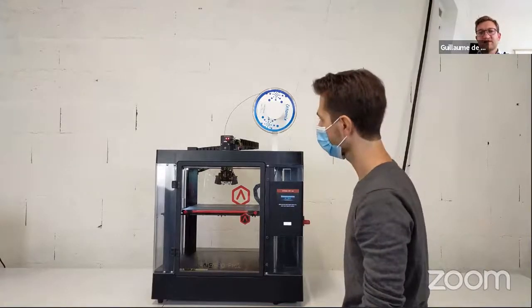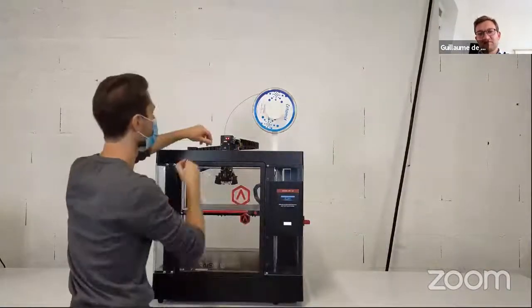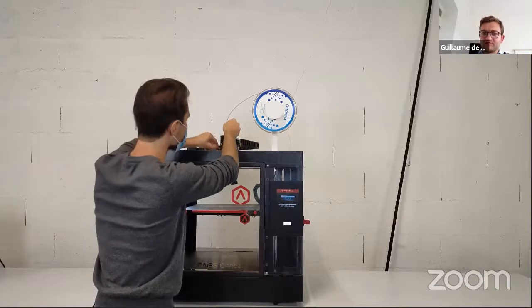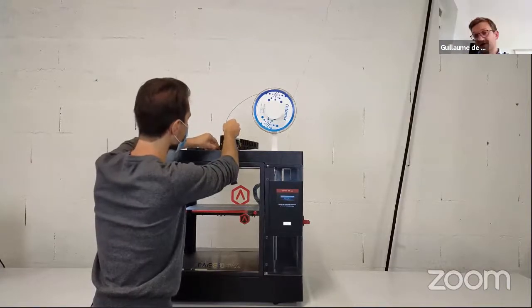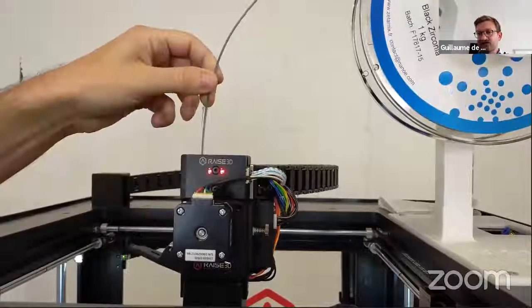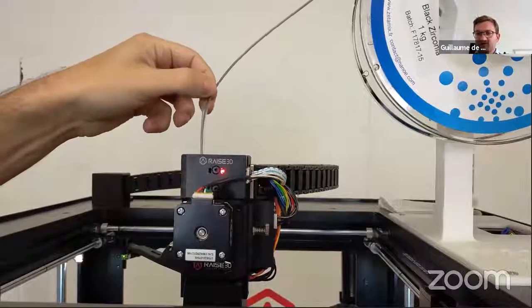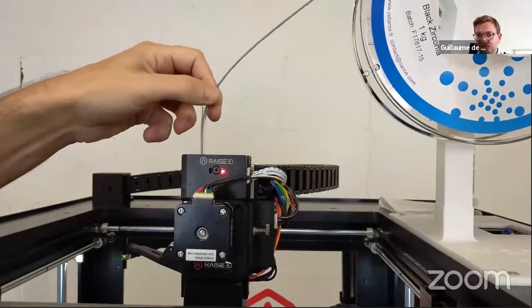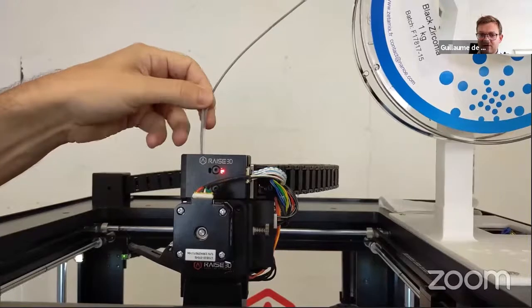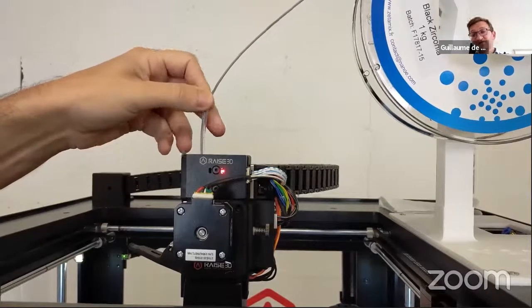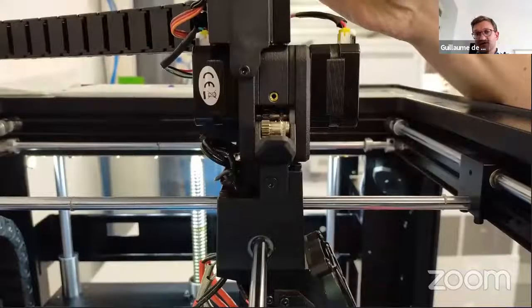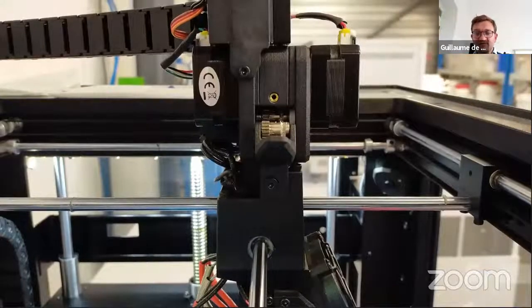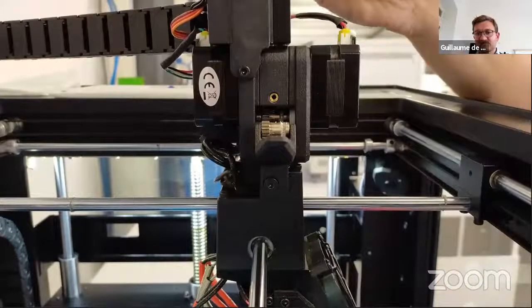You will notice that the operator is quite careful during the loading because the filament is quite brittle. This is also why we put it on an adapted spool holder, because of the brittleness of the filament. So loading is quite simple. We're just going to push the filament in the gears. Here we just open the gears so that you can see what happens. Usually it's closed.